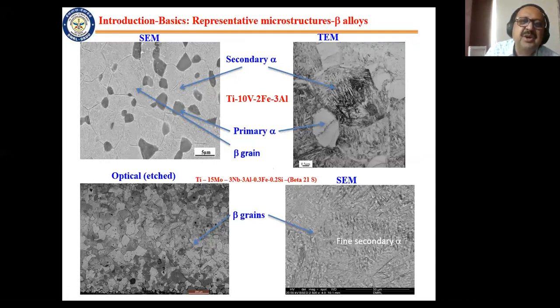So here I am showing you a microstructure of alloy Ti-10V-2Fe-3Al, which is used for landing gears of aircraft. And here again, what you see is dark colored primary alpha, which is limiting the beta grain sizes, and inside you have very fine alpha. Now this fine alpha is precipitated at a different stage. Once you have aged this alloy, then only this fine alpha precipitates and gives it high strength.